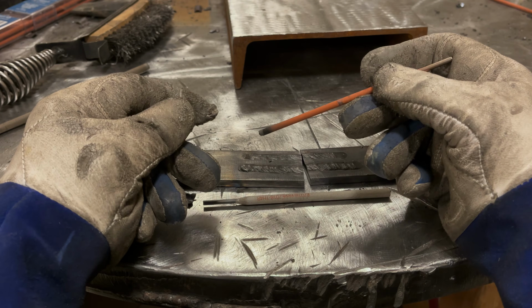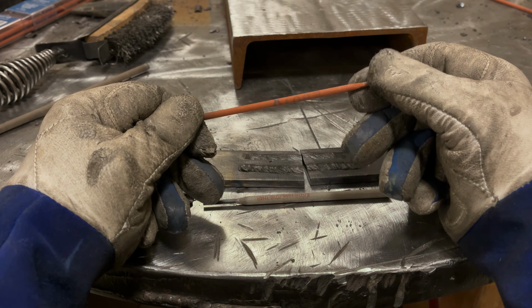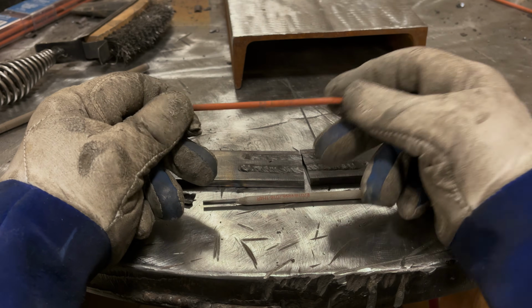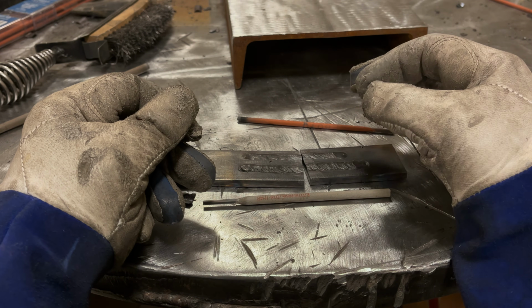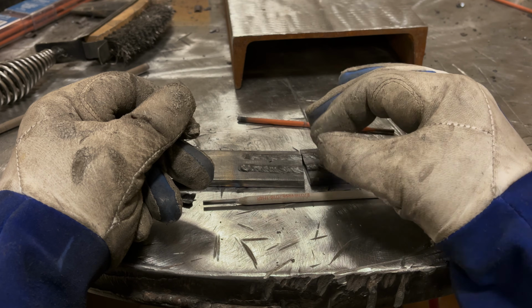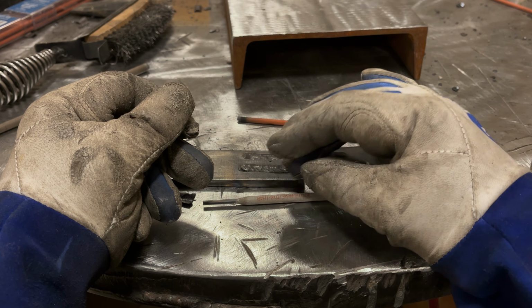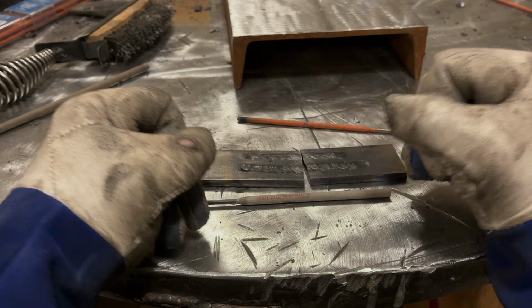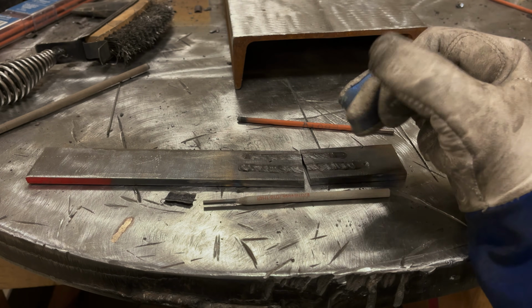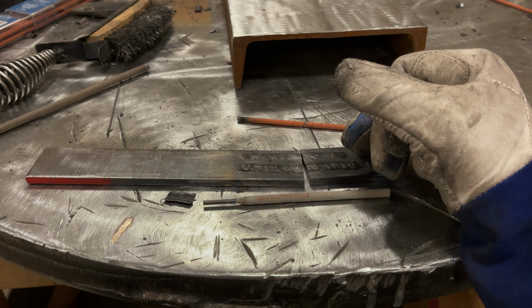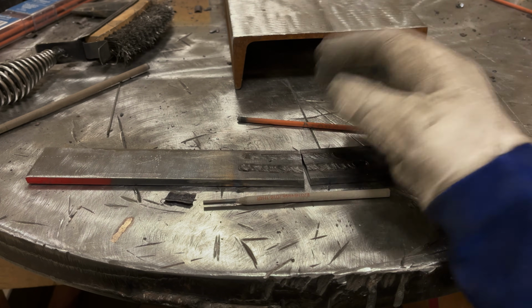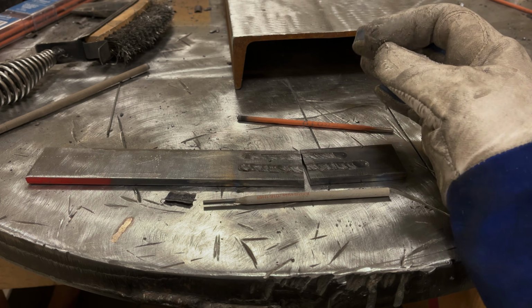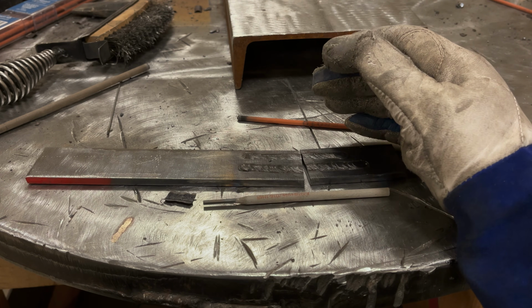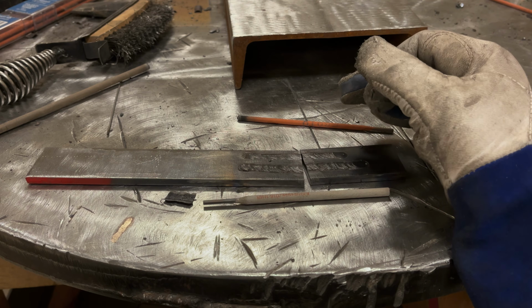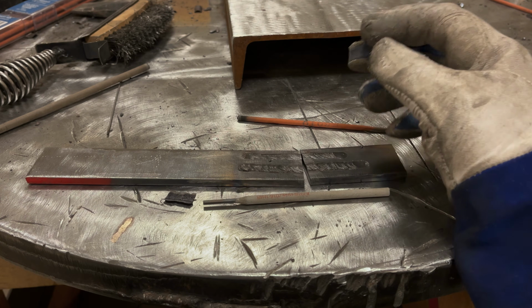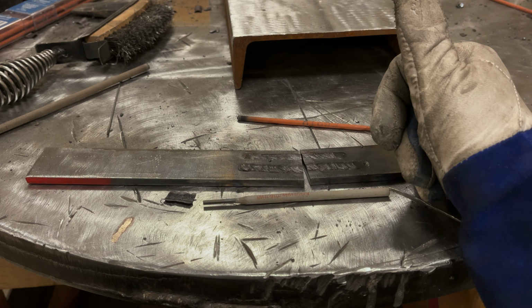The same thing happens with MIG that happens with stick. So that's why this particular rod, 6010, has more arc force. It has a different shielding gas covering the molten pool, and the flux as well. And that shielding gas helps transfer more heat through the arc gap into the metal. It's the same reason why, in TIG welding, when you use 100% helium versus 100% argon, the weld with helium has more penetration and is hotter. The reason is that it ups your arc voltage.